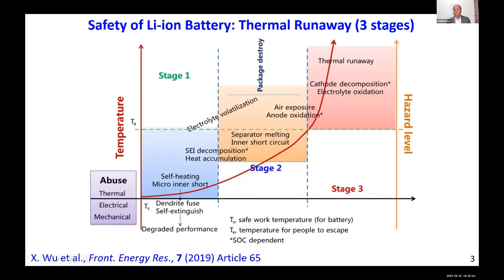If you allow this to continue, then what happens? Heat accumulates. The so-called SEI, solid electrolyte interface, is formed on the surface of the graphite, because graphite is operating at below 1 volt versus lithium. Lithium is at 0 potential, and anything that operates below 1 volt, you will have a reaction between the anode and the electrolyte, forming the so-called solid electrolyte interface, which is a polymer layer. This starts decomposing because of the heat accumulation.